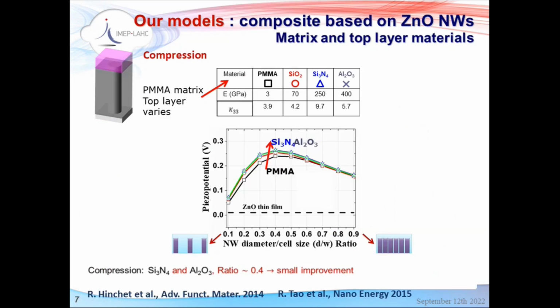So with this kind of simple models, we can extract much information. For instance, we can play with the dielectric material that we put on the top. We are using PMMA, which is a polymer, but we can change it. We can put oxides or nitrides, go into something more rigid, for instance. And we can play also with the density of the nanowires, meaning how far they are from each other or how close they are. So what I present here is a simulation of the piezoelectric potential as a function of this density, and also as a function of the different dielectric materials.